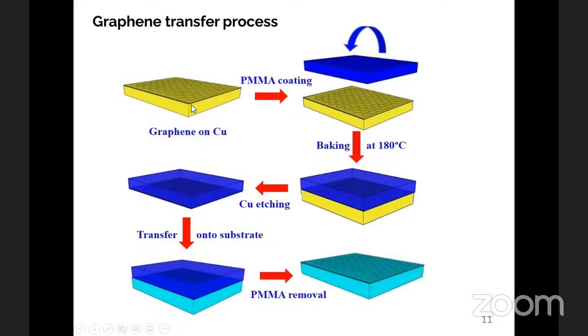Of course, copper is a metal, and graphene is almost like a semi-metal or metal. So I don't need the copper in my case, because I need to transfer the graphene onto a semiconducting or semi-insulating substrate for my device applications. So I need to etch the copper underlying the graphene. This is a standard wet transfer process for graphene that involves PMMA coating. The PMMA will strongly hold your graphene when you bake it at 180 degrees Celsius, and the copper underlying the graphene can be etched using ammonium chloride or ferric chloride solutions. Once the copper is etched, the PMMA with graphene can be transferred onto the desired substrate like silicon dioxide or silicon, and then the PMMA is removed using acetone.